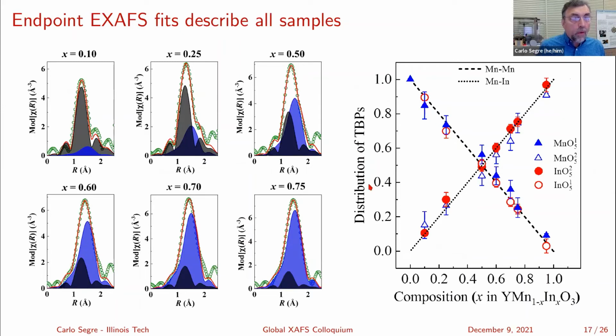And as you can see, we get quite good fits all the way. Remember, 0.05 is one of our endpoints, and 0 is our other endpoint, and 0.95 is the other endpoint, of course. So we get very good fits out to about 2 angstroms for just a linear combination of these data sets. This is the manganese edge, and we did the same thing with the indium edge. We took 2 endpoints that we had. We didn't have x equals 0, so we took something as close as possible to full indium. And actually, we did have it.